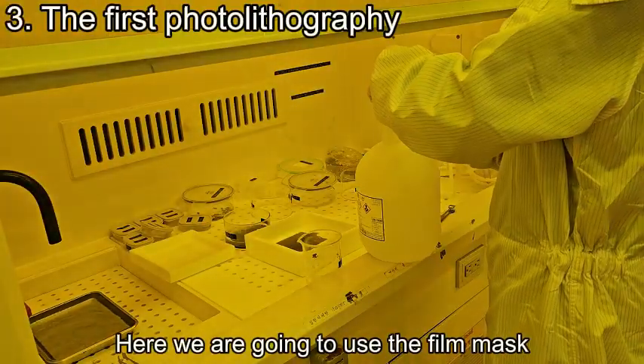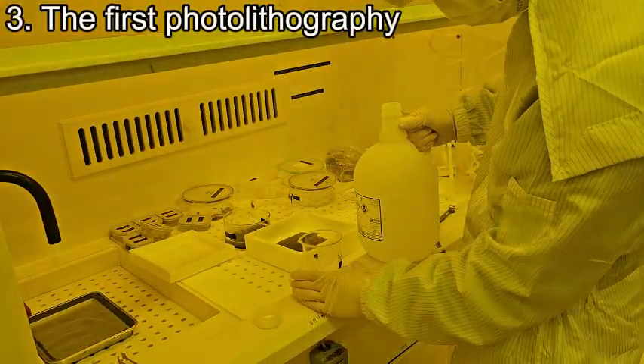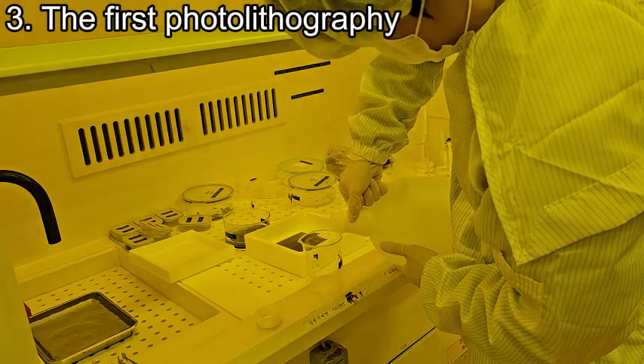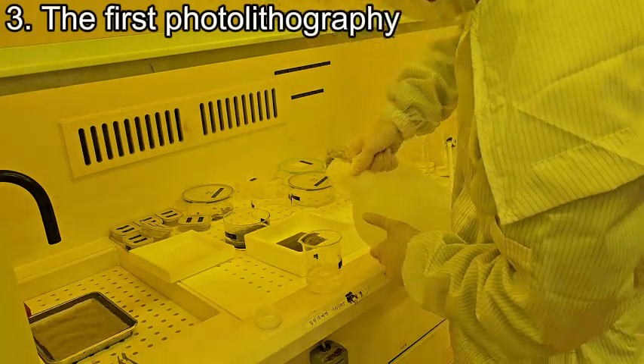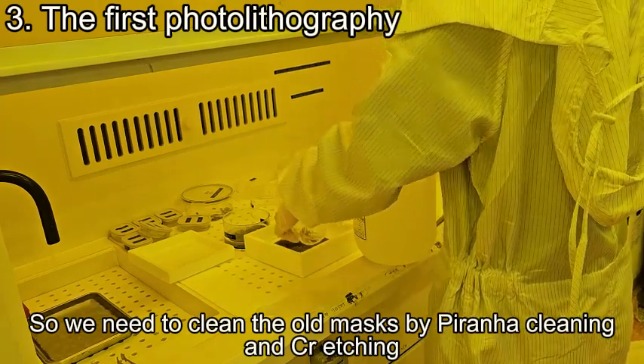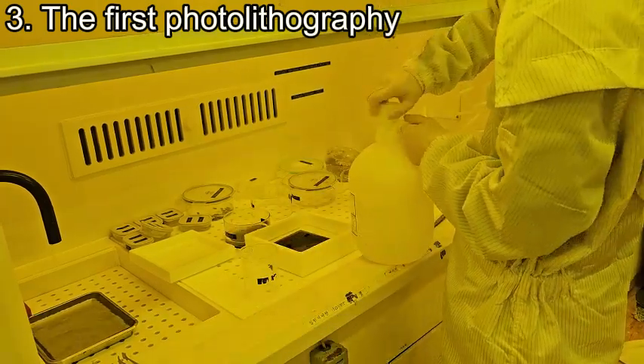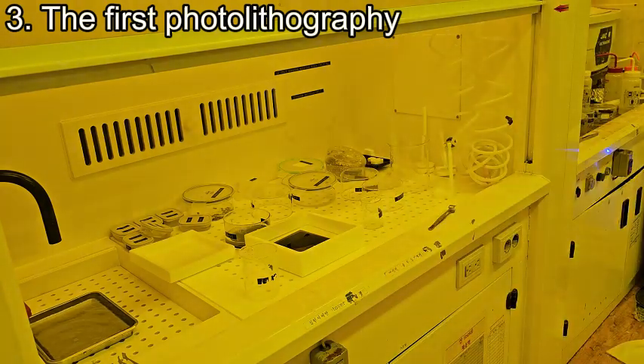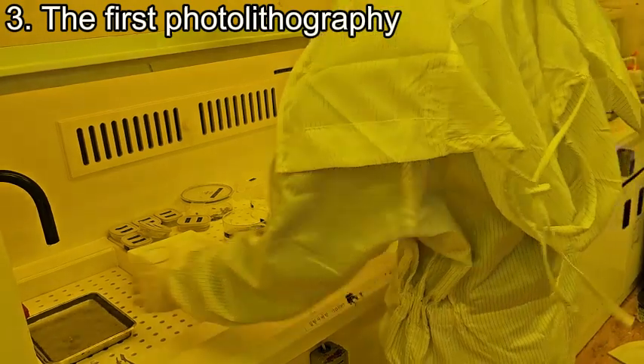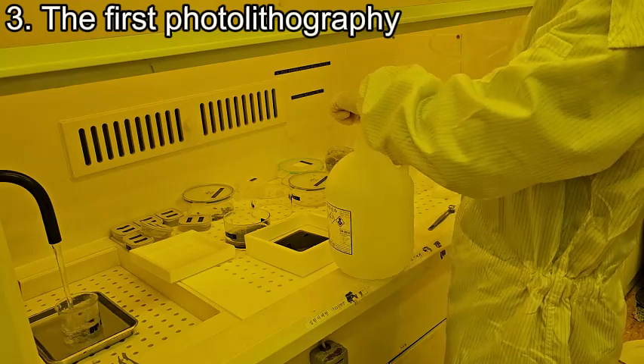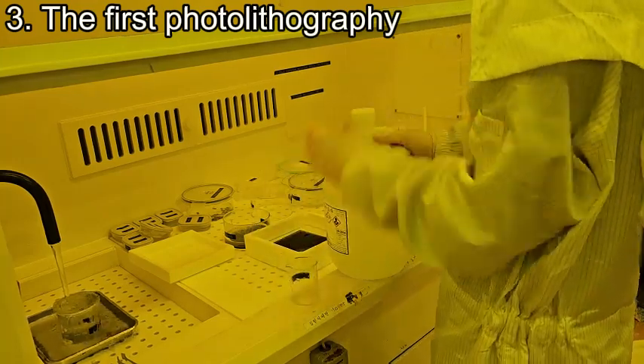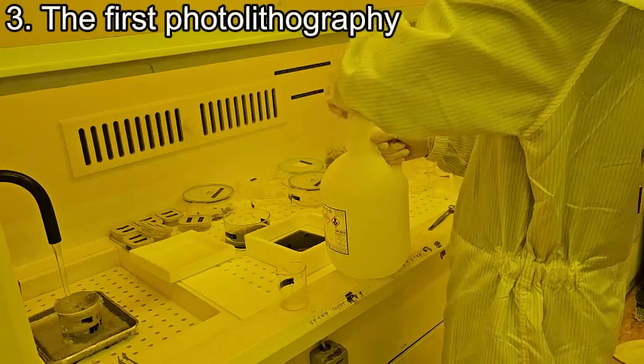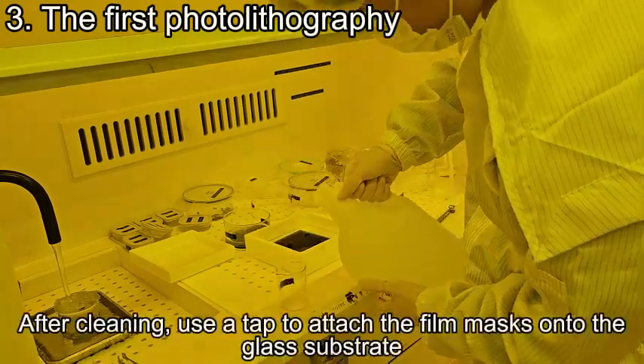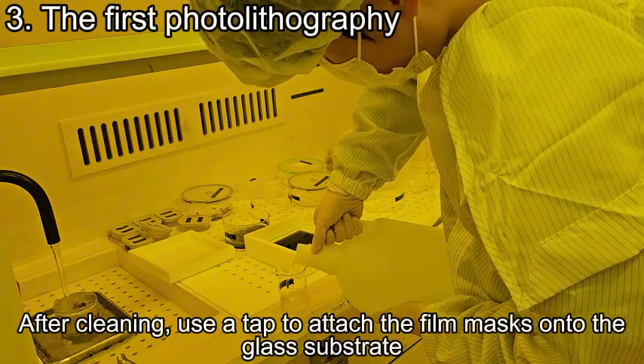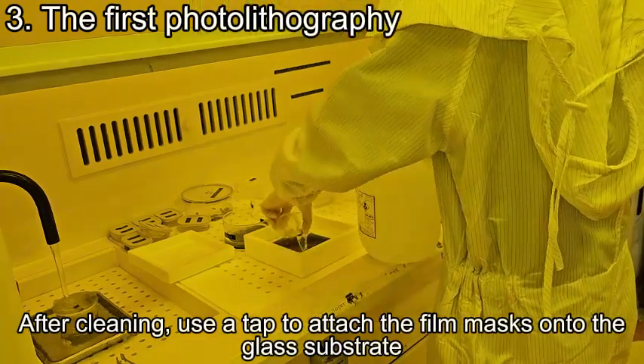Here we are going to use the film mask. So we need to clean the old masks by piranha cleaning and Cr etching. After cleaning, use a tape to attach the film masks onto the glass substrate.